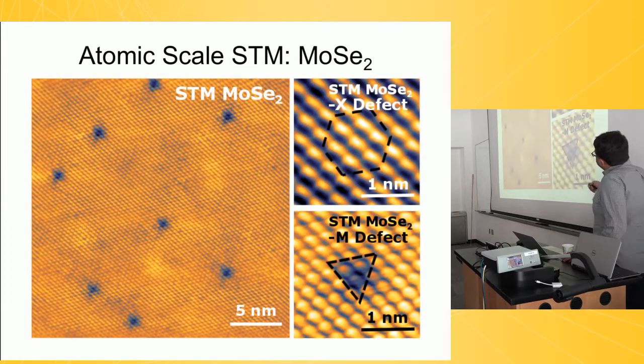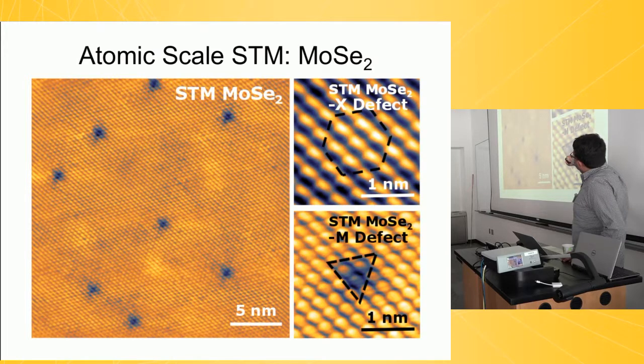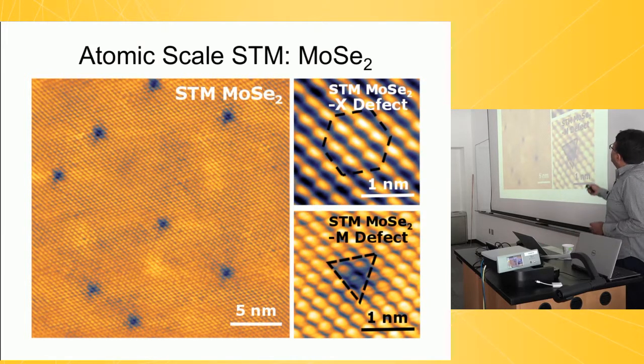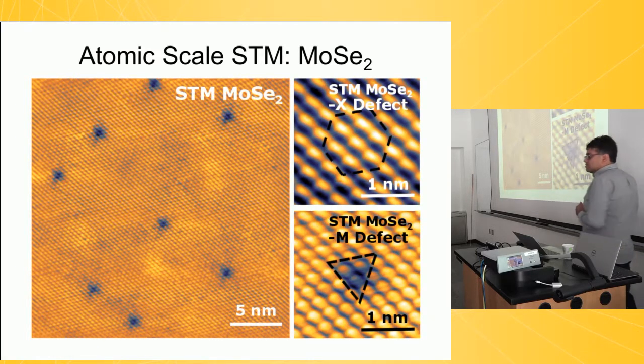Okay. So here's now a zoom in. You can start to see the lattice. And these are the chalcogen atoms on the surface. And if you zoom in, you'll see that all of the defects that we see with greater than 99% probability fall into what we call the dark defect here and the bright defect there. And these bright defects are always centered on the chalcogen site. The dark defect is always centered between 3 chalcogens, so it's centered on the metal atom.